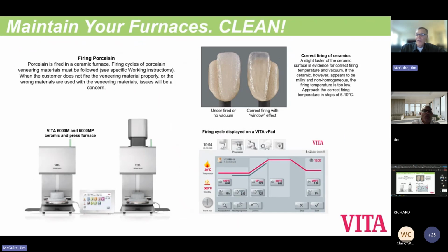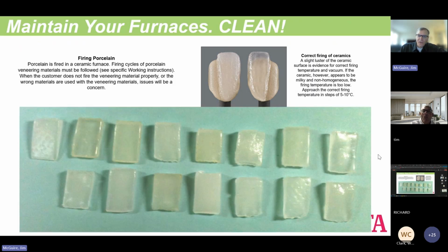Make sure that if you have your own furnace, if you're doing some of this stuff, make sure it is clean. If you don't clean your furnace routinely, all the oxides, all the bad things that get fired in your furnace, instead of a clear window, these happen to be almost 20 different labs that we had produce different window samples from their furnaces, and you can see the variation. It's impossible to get the correct shade if you're firing something and the glaze doesn't come out clear. You need to adjust that accordingly and clean it up.